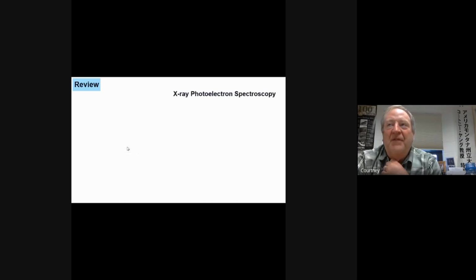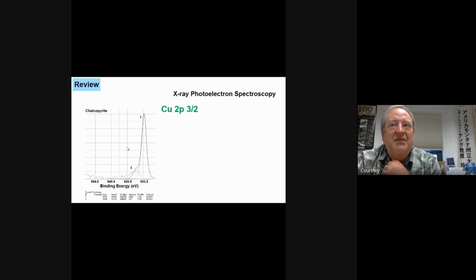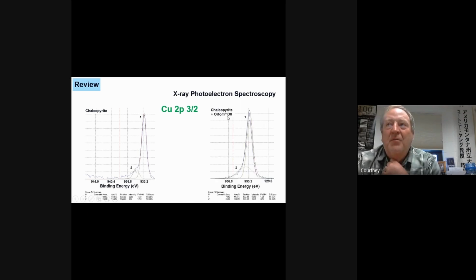Okay, so if it's electrochemically active, then maybe we can see something by X-ray photoelectron spectroscopy. So we're going to take a look at the copper 2p 3/2 peak, and this is just chalcopyrite. So you see a peak here at 933.4, somewhere in there, or 933, and then you see a second peak in here. Okay, and this peak is the one we're going to monitor. And we're going to compare that with chalcopyrite with Orfom D8 present. And here's the peak 1. It's the same position. So we don't care about that one. It's this guy that we're seeing a change in.